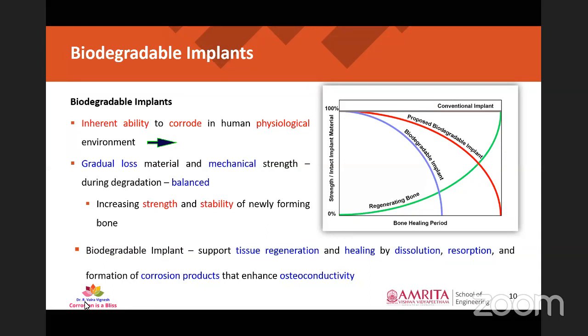So we have to ensure that the proposed biodegradable implant will have gradual loss in material and mechanical strength during the degradation process, and that has to be balanced by the increasing strength and stability of the newly forming bone. And added to that, the biodegradable implant should also support tissue regeneration and healing by dissolution, resorption, and formation of corrosion products that enhance osteoconductivity. So it means that the cells near the bone and the implant should consider that implant material as its own, and it should develop a habit of forming new tissues near the implant material so that we'll get the healing period in somewhat lesser time.